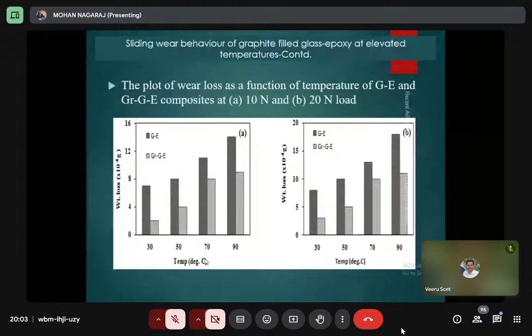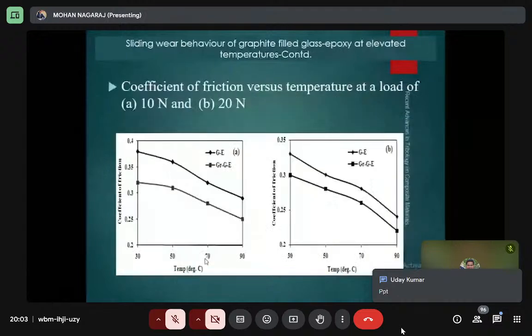And also the coefficient of friction is one of the very important phenomena we studied in the graphite filled composite materials. Here the graphite filled composite gives a lower coefficient of friction because of the solid lubricant. There is a formation of a thin film in between the two components. So this enhances the wear resistance of materials, and the thin film between the composite specimen gives good lubrication properties. There is no need to add any extra lubrication. It is inherent in the property of the materials; the action takes place by itself.